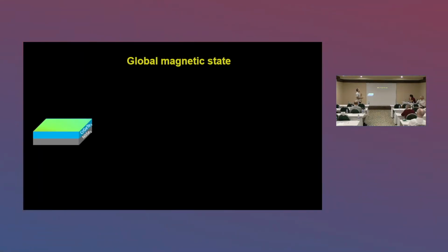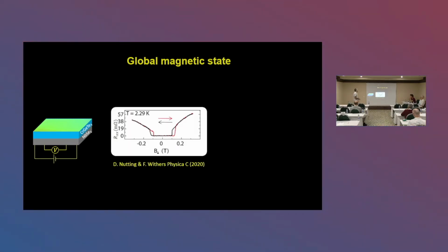Another experiment, and this is more related to the title of vortex dynamics, is to proximitize this ferromagnet with a superconductor and measure just the longitudinal resistance. This was done by another group, and they found that at a constant current, if you look at the magnetoresistance, you have a hysteretic behavior around some sort of coercive field, and they were not so sure how to interpret this data. So this was a good opportunity for us: wherever there is an unsolved transport mystery, maybe microscopy can help.